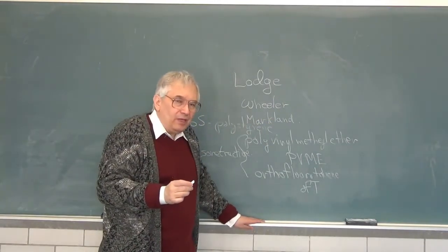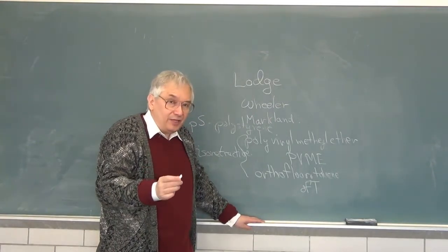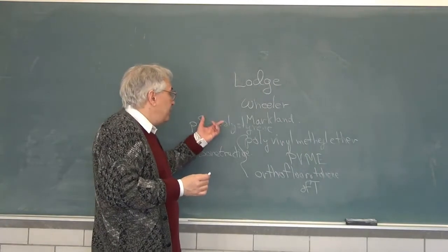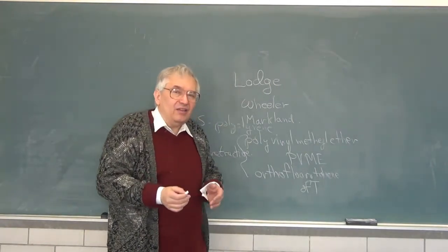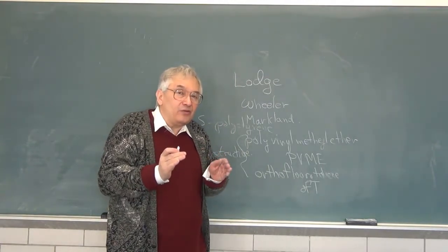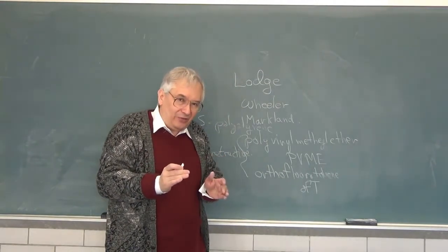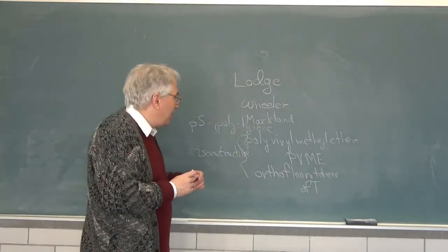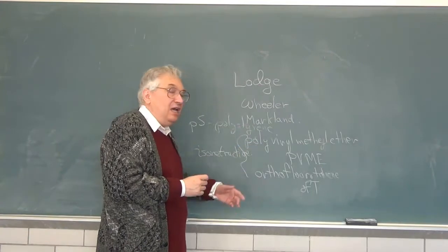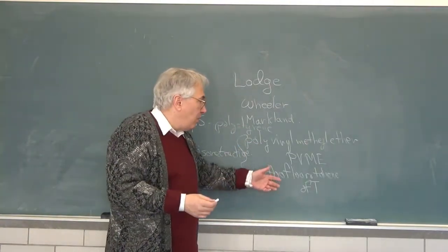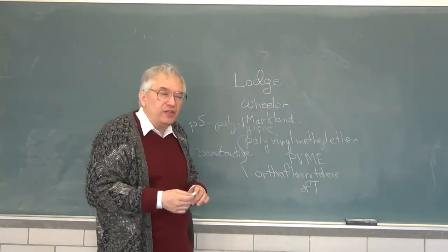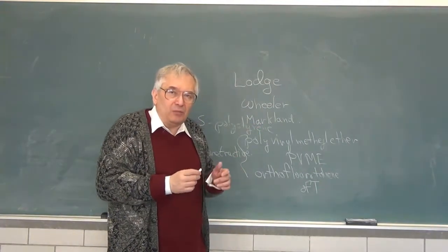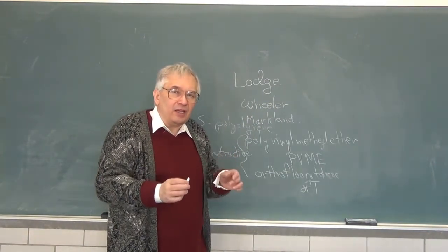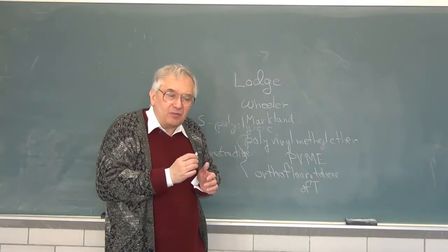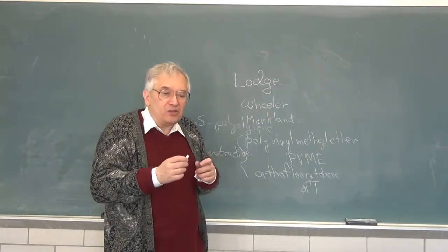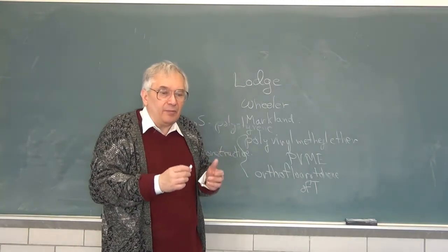Polystyrene as a probe for this system has two enormous advantages. The first advantage is that you can make polystyrenes synthetically that are very pure in their molecular weight distribution, so you know exactly what the molecular weight of the polymer is. The second statement about polystyrene and PVME is that they're compatible, so that OFT is a usable solvent with both of these materials, and the two polymers mixed together, rather than having some very negative thermodynamic interaction which causes them to fold up. And that's very useful because it means you know that the probe behavior is reasonably well behaved.